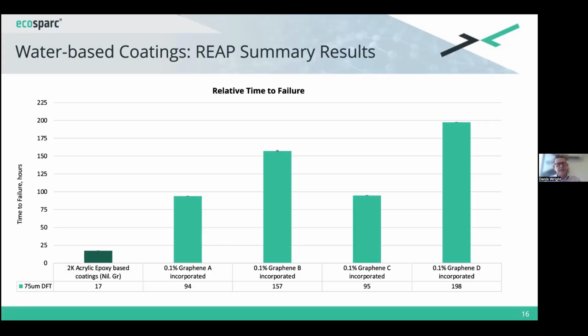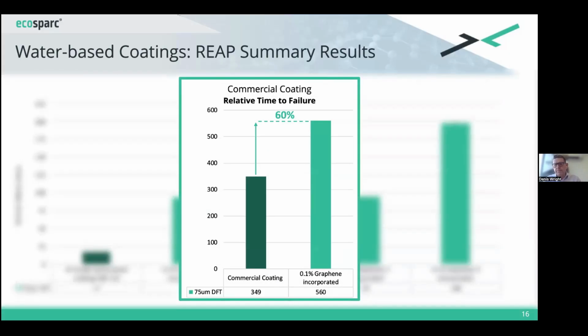Once we got the good indicative results, we then got a commercial coating, 2-pack epoxy water-based coating again, and we added graphene-based additive into it. And in the REAP testing again, the accelerated testing, it's via an EIS procedure. We got a significant improvement in the performance. The next obvious step is, okay, that's accelerated. Let's put it into a salt spray set of tests, and that's what's underway right now. We're doing that right now.